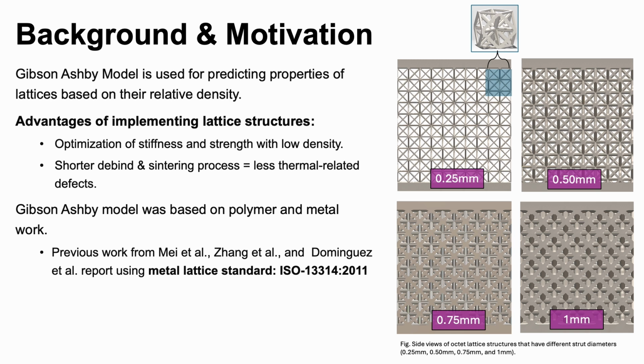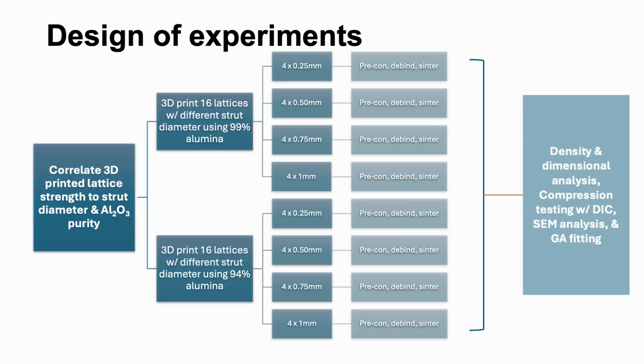For this work, I used the octa-unit cell design seen here and translated it 5 times in the XYZ direction to form a lattice structure. I changed the strut diameters from 0.25 to 0.5 to 0.75 and 1 millimeter to change the lattice densities. I made the following design of experiments for this work.